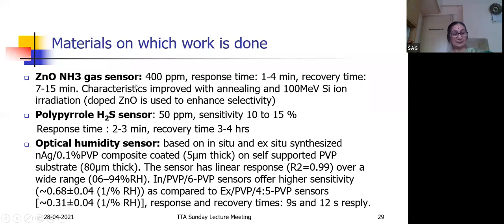And these characteristics could be improved by annealing or irradiation of the sensors, by silicon irradiation. And we could get a change in the sensing characteristics. It especially improved the sensitivity of the sensor, so we could go to a smaller level of ppm.